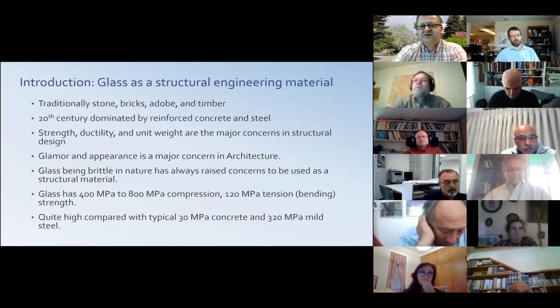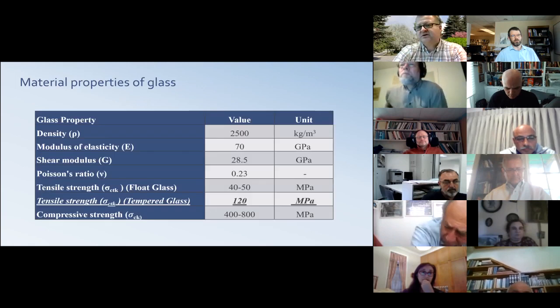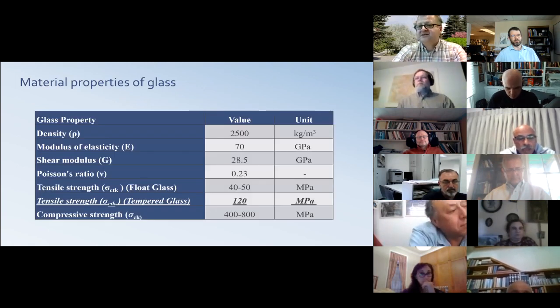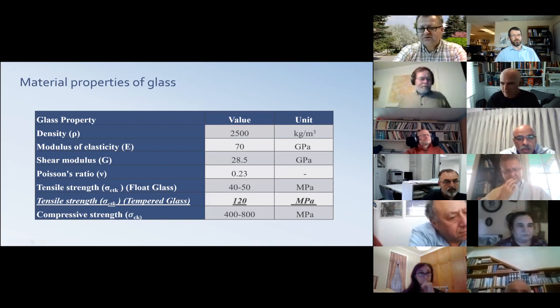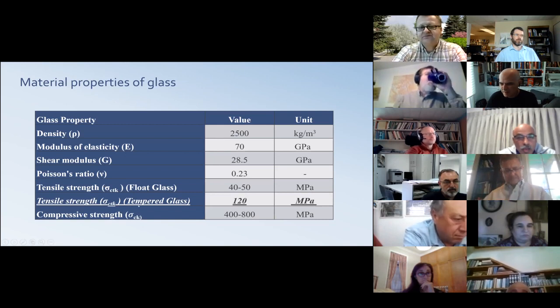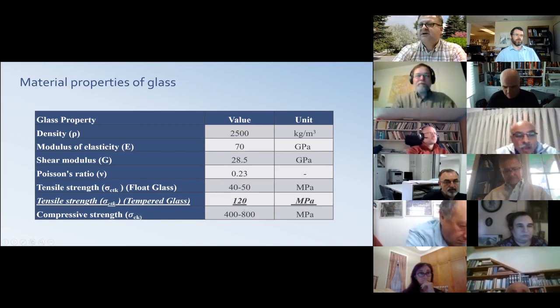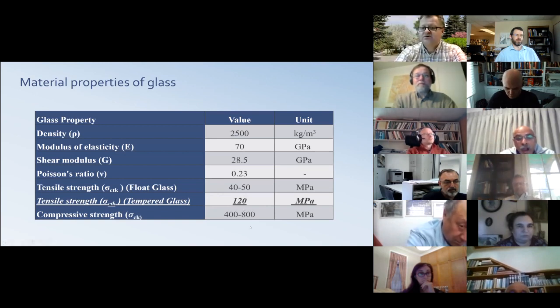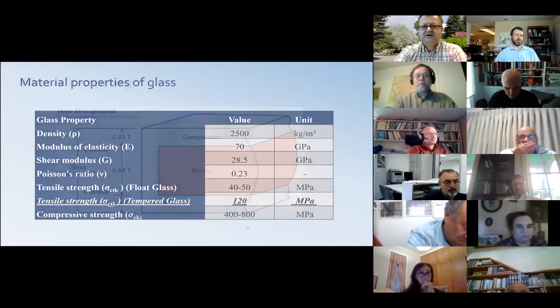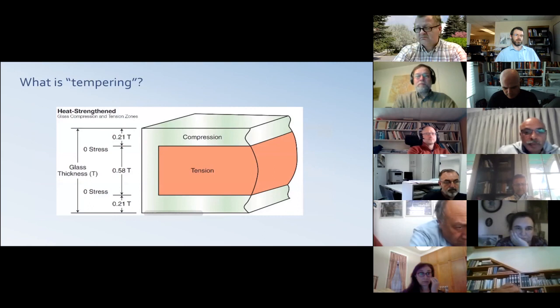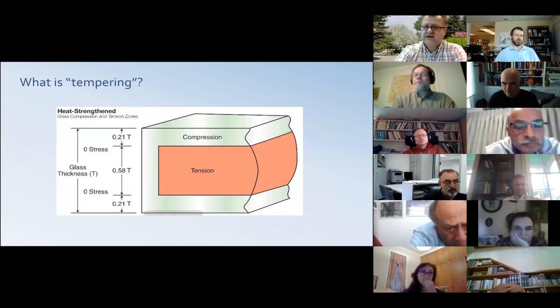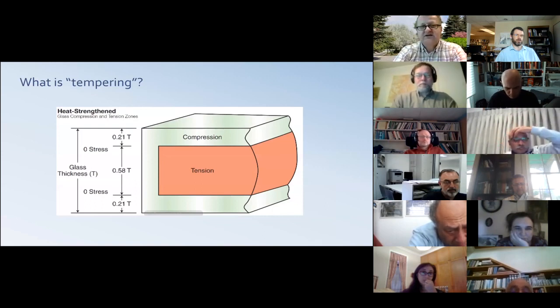Probably because we don't trust it, because, well, it basically cracks and breaks. So 40 to 50 megapascal of tensile strength for floating glass, and about 120 megapascal for the tempered glass, and all the way to almost 1 gigapascal is a very superior strength. With this new glass, there are ways we can prevent cracking. One of them is post-tensioning, and this is what we have investigated in this study.